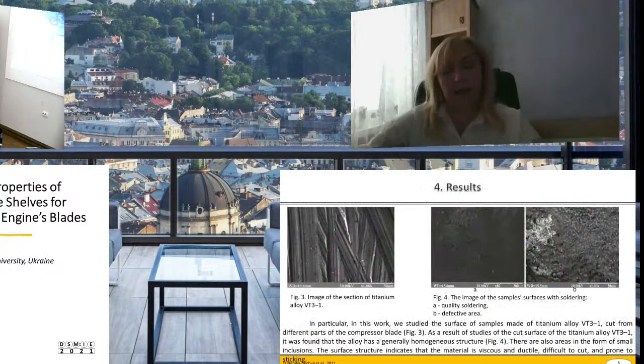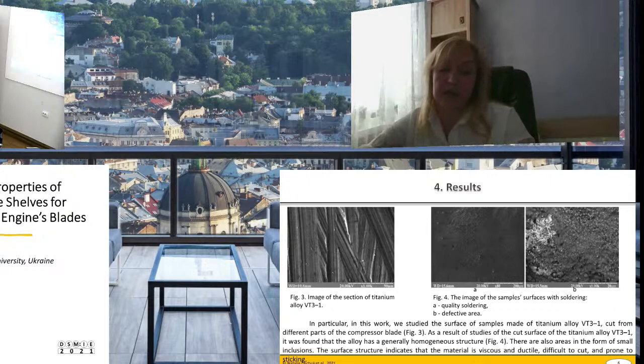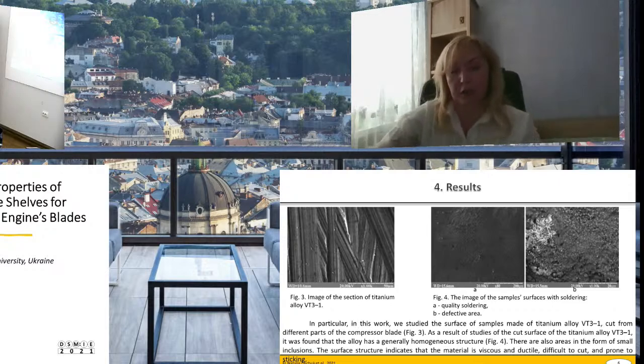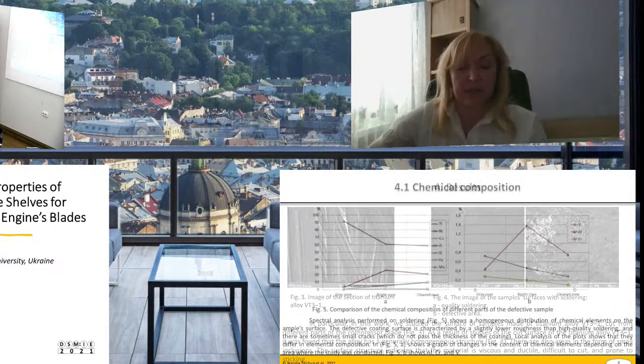On the next slide, we can see an image of the section of titanium alloy VT3-1 and the image of the sample surface with soldering, with quality soldering and a defective area. In particular, in this work, we studied the surface of samples made of titanium alloy VT3-1 cut from different parts of the compressor blade. The surface structure indicates that the material is viscous and ductile, difficult to cut and prone to sticking. Next slide, please.